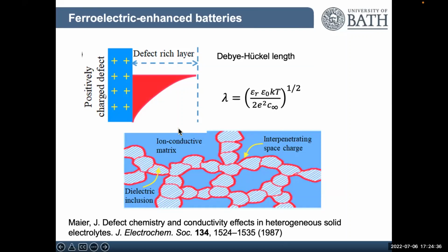And I think one of the most interesting areas is that these ferroelectric materials are high permittivity materials. And if you have a ferroelectric or a dielectric inclusion within your ion conductive matrix, there's this very nice work by Maier that says, well, what you do on the interface is develop a space charge, and you develop a defect-rich region between your dielectric inclusion and your conductive matrix. And if you look at the Debye-Huckel length, that length of your defect-rich region has a strong relationship to the permittivity of the material. And obviously these ferroelectric materials are highly polar, so you have very high permittivities.